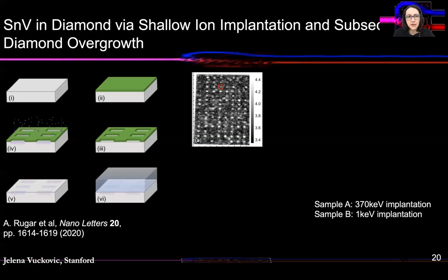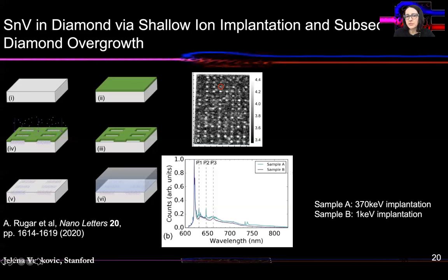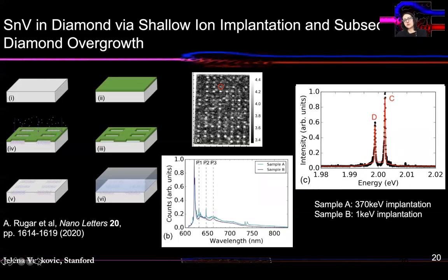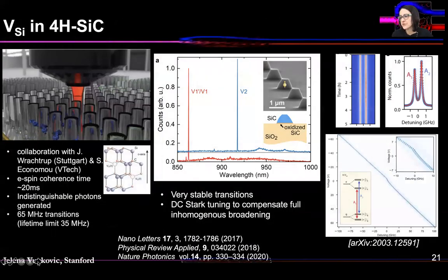The idea is pretty simple. You mask high purity diamond, you bombard it with low energy ions of silicon or tin, and that leads to shallow implantation close to the surface. Then you grow a high purity layer on top to cap these color centers. As a result, you have regular arrays of tin vacancies here, with minimal damage to the structure, which leads to elimination of some unwanted peaks in the spectrum that are a result of damage, as you see here in the blue spectrum. And you also achieve much narrower line widths of the transitions of the color center, again as a result of the much lower damage to the structure. So our color centers in diamond are now introduced by using this very simple method that leads to superior properties.